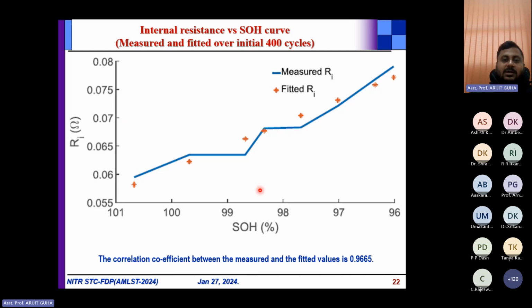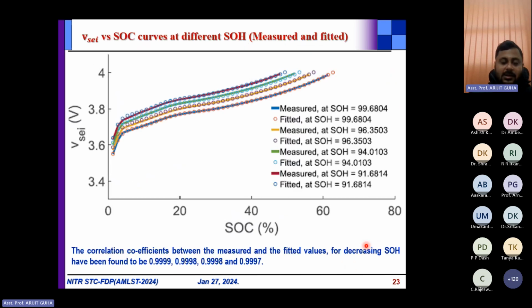Now this is the internal resistance versus SOH curve, and it is a measured and fitted one over the initial 400 cycles. One is the measured one, the blue one, and the fitted one is shown here in the red dots that you can see here, and we have observed that the correlation coefficient is around 0.96. Now this is a v_sei versus SOC graph for different stages of aging. That's why it has been written here that when SOH was 99%, this is the measured one.